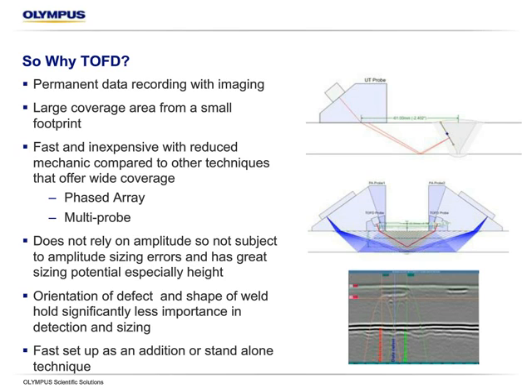Because we use time of flight, we're not subject to those amplitude sizing errors anymore. We're using time, which is absolute. We're able to get much better precision on our sizing typically. And really, in height, the height plane and the depth plane can be quite excellent with TOFD. Also, it has a pretty indifference to the orientation of the defect.